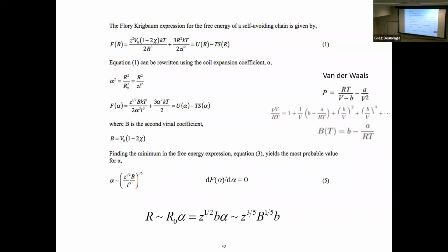It's actually like a 3-step thing that does the entire Flory-Krigbaum. Actually, this is kind of interesting in and of itself that he could do that. And he doesn't seem to use that approximation, the thing about dropping terms. And yet he gets exactly the 3/5 law, which we know isn't exactly right. That's 1.67. The actual answer is 1.72. So something weird about this, but this is actually the whole Flory-Krigbaum in one step, you know. So it's kind of interesting he can do that. So there's some merit in this alpha thing, I guess.